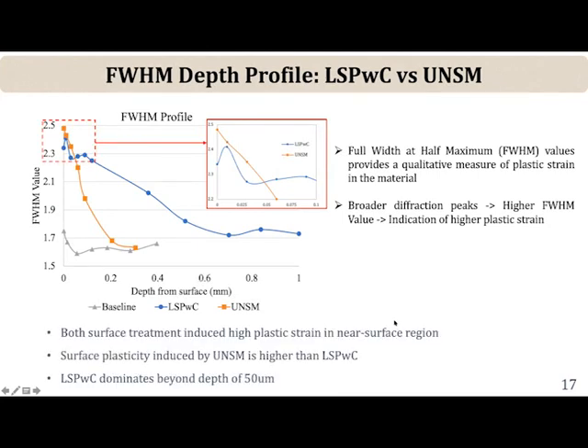The other important quantity is, as I mentioned, the compressive residual stress is just only one part of the problem, right? The other is the change in microstructure and the increase in dislocation density and in the formation of these crystallites, right? Both LSP as well as UNSM, you can regard them as kind of ultra high strain rate deformation, right? It's plastic deformation. So the dislocation density is going to increase. You're going to form subgrains, crystallites, which are highly misoriented. So the consequence of having crystallites and having high dislocation density is that you get broadening of the diffraction peaks. And the extent of broadening of the diffraction peaks can be used as a measure of the level of plastic strain at the surface, as well as a measure of the crystallite size.